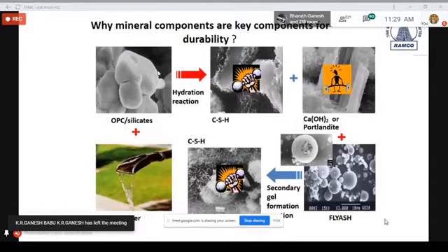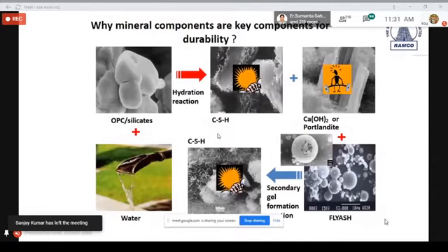Why is it so interesting? You have seen the various kinds of attack that concrete faces: the carbonation, the chloride attack, the sulfate attack. By virtue of the formation of CSH gel in huge quantities, the concrete will be much more impermeable by virtue of its imperviousness. Various concrete attacks are stopped because of the CSH gel. So that is why the secondary gel formation in the case of Portland Pozzolana cement, fly ash based cement, is very interesting, so that your CSH gel and your impermeability is enhanced.